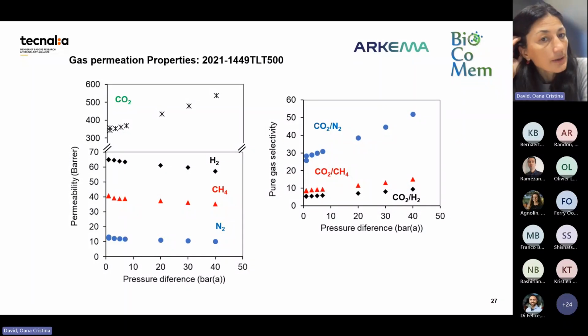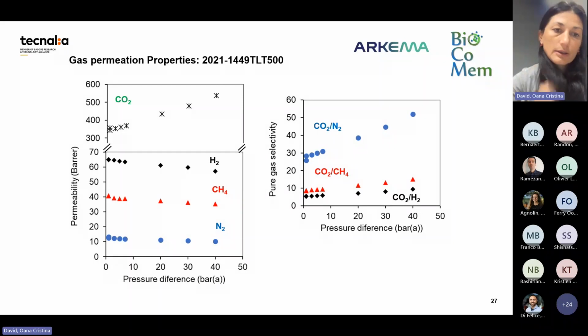With dense sheet films of these polymers, we double check their gas permeation properties also by varying the feed pressure. So here we went up to pressure of 40 bars. We see that there is an increase in carbon dioxide permeability, reaching values of more than 500 barrer. And the other gases have more or less constant permeability. This is why the selectivity of carbon dioxide to nitrogen and to the other gases increases with pressure, but increases more for carbon dioxide to nitrogen, and we reach values of about 50, which is very nice.